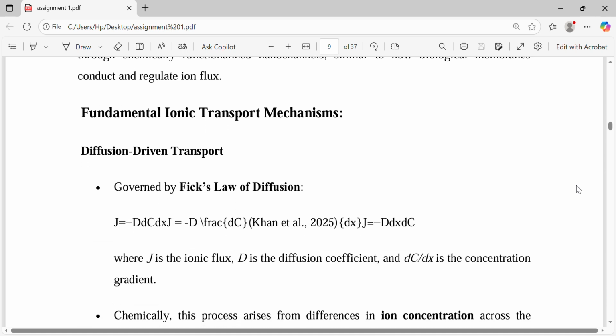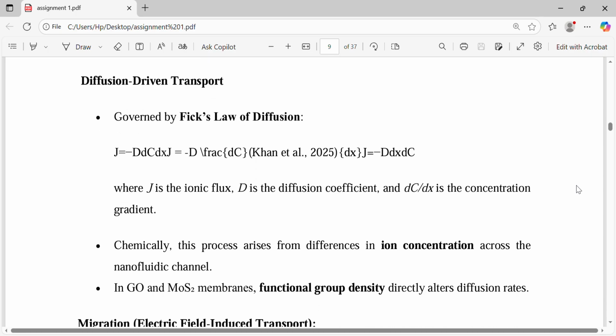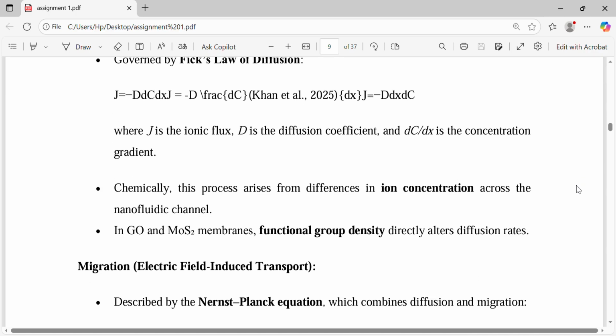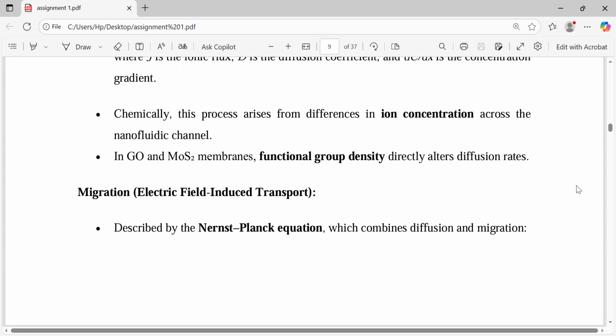Fundamental ionic transport mechanisms. Diffusion: transport governed by Fick's law of diffusion, J equals minus D dC/dx, where J is the ionic flux, D is the diffusion coefficient, and dC/dx is the concentration gradient. Chemically, these processes arise from differences in ion concentration across the nanofluidic channels. In GO and MoS2 membranes, functional group density directly alters diffusion rates.